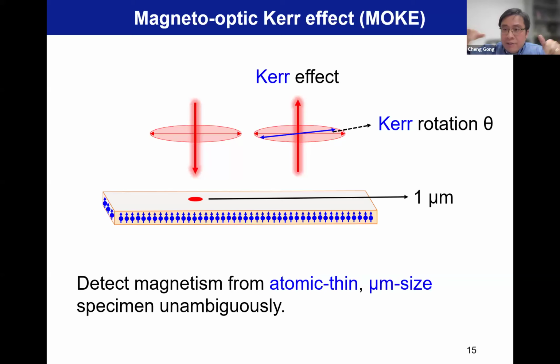If the left and right circular polarized light have a phase difference upon reflection, you will cause a Kerr rotation. If they have different reflectance, then you will have the so-called magnetic circular dichroism. That means you will not only have a rotation, but it will not be perfectly linear light. It will become elliptical. In the old days, like 30 years ago, in the 1990s, when MOKE became popular,